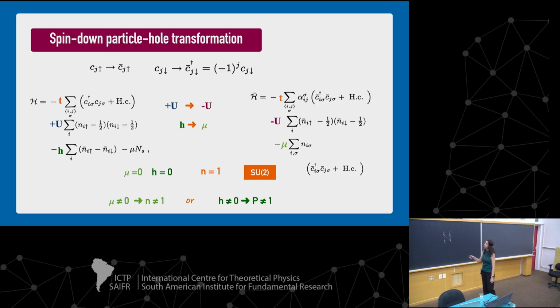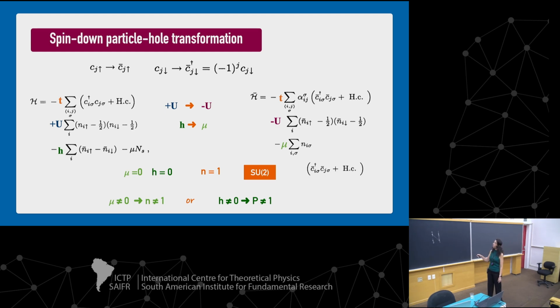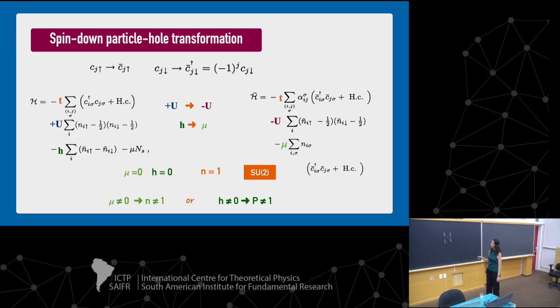And when I plug this into the Hamiltonian, this is what happens. So this is the original Hamiltonian in the presence of a magnetic field and chemical potential, and this is the attractive Hubbard model. So when I do this, I turn plus U into minus U because of this sign here, and I turn the magnetic field into a chemical potential. And so if I have no magnetic field and no chemical potential, the two first lines turn into each other, and I have a half-filling SU(2) model with mu equals 0 and H equals 0.